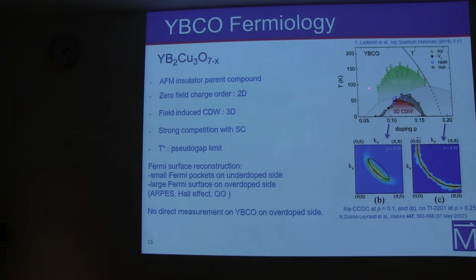So this 2D charge order is present at zero magnetic field, and that's an important point. And more recently, it was found that there is a second charge order, this time 3D, that shares some characteristics with the 2D, but this one develops only at high magnetic fields, so above 18 Tesla, and that's an important point here in the story.